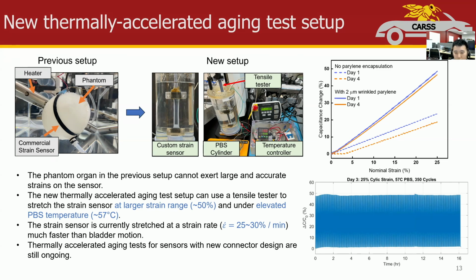As you can see on the right, we are currently testing the sensor with only Parylene encapsulation. Over the span of 4 days, the encapsulated sensor showed minimal changes in its performance, and the signal was very stable, while the non-encapsulated one has a very large change in its performance. To improve this, we will also apply the inorganic layer and further optimize the encapsulation for the rest of the sensor components.